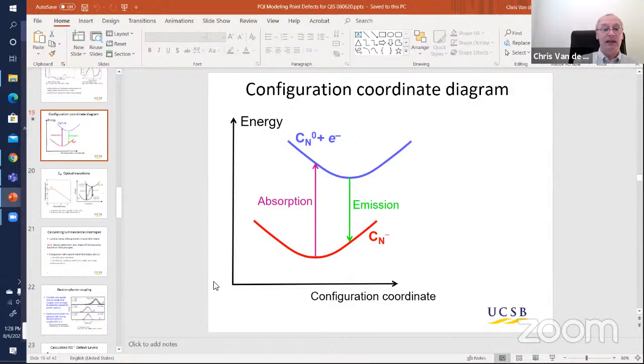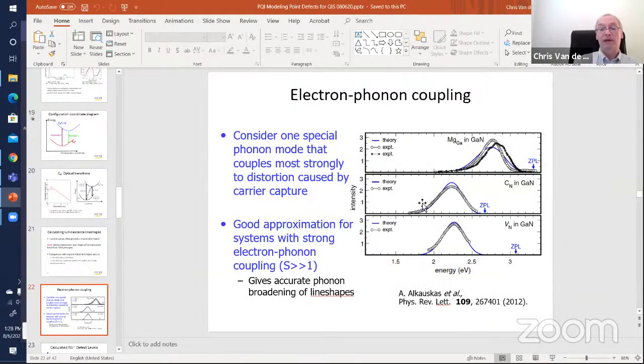And again, in the cases where we've done our benchmarking, where those Huang-Rhys factors have been experimentally determined, our calculated values are very close to the experimental values. We have actually also used that in our identification of these centers in hexagonal boron nitride that I talked about. The Huang-Rhys factor has been experimentally measured for those centers. We can calculate it, and for the centers that I proposed, the agreement is very good.